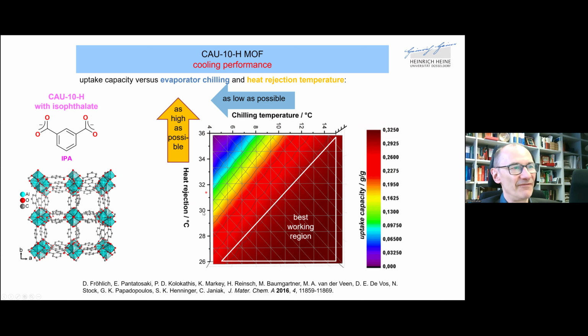For example, if the heat rejection is done at 30 degrees centigrade, you could have, at the lowest, a chilling temperature of 10 degrees centigrade to still be in this white triangle. And if you go to 36 degrees centigrade for the heat rejection, because I said it should be as high as possible, then the chilling temperature could only be around 14 or 15 degrees centigrade. So it could not go down as low as would perhaps be desirable, so that the uptake is still as high as possible. So this is the engineering map of the constraints which should be fulfilled by this material. Actually, the material from which this plot is made is CAU-10-H with the isophthalate linker, which I had shown to you before.